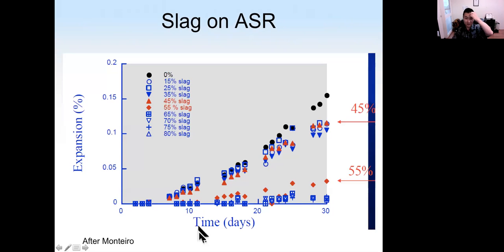Okay, and here shows the result for slag. Okay, so we have different series of concrete with different percentage of slag, from 0 to 15 to 45 to 55 to 80% of slag. Okay, so what we can see here is we increase the dosage of slag, the expansion becomes smaller. Okay, but we have a big jump between 45% and 55%. So that means maybe the best percentage for reducing ASR using slag is 55%. If we further increase slag, we will not see a big reduction in expansion. Okay, again, this is just an example of studying the effect of mineral admixtures on ASR.